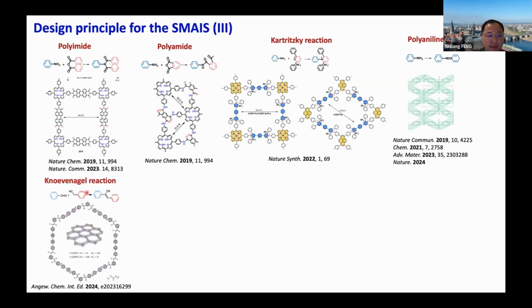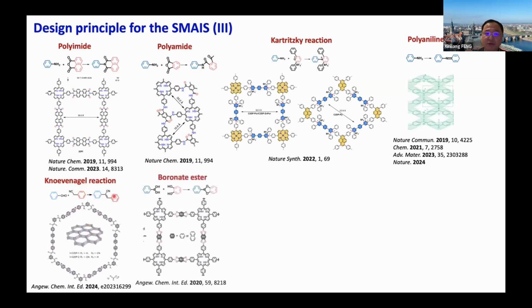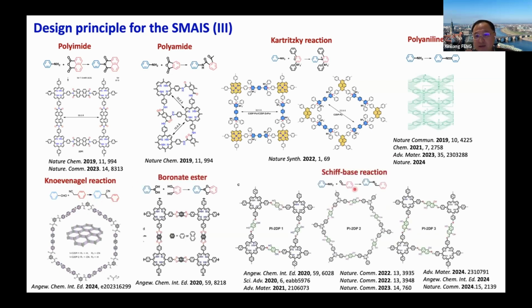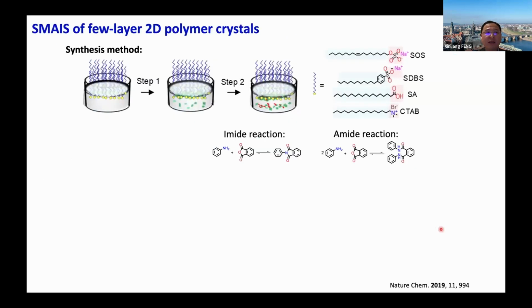The carbon-carbon bond, like a Knoevenagel reaction, but also the dynamic covalent reaction, like a imine double bond with the Schiff-base reaction, that all these beautiful structures can be made on this water surface down to monolayer to few-layer level. And the first case is so-called polyimide, polyamide.